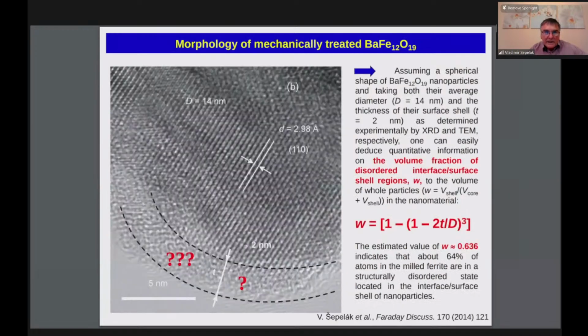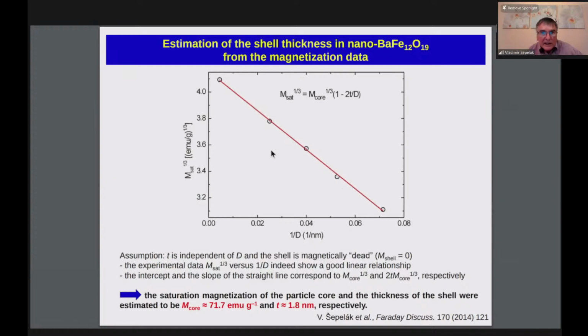And here is again the morphology of such mechanosynthesized nanomaterials, and we see that these surface layers or interfacial regions are disordered due to this shifting of iron cations from 12K sites to interstitial sites, which can lead to the dead layer, magnetically dead layer. That means a layer with magnetization equal to 0. And in this case, we can also, from magnetization data, calculate the thickness of this surface shell, and it was in very good agreement with visual information from transmission electron microscopy. From magnetization measurements we obtained the thickness of this surface shell of about 1.8 nanometers.